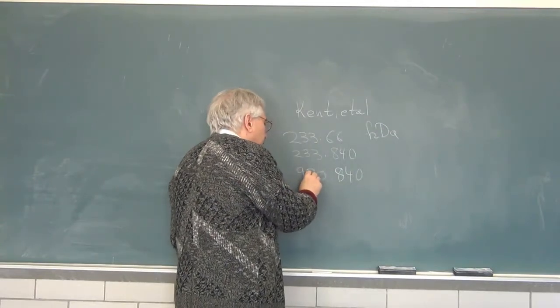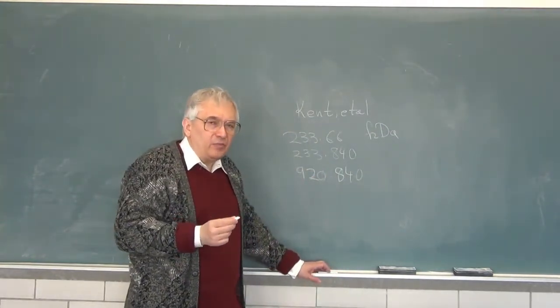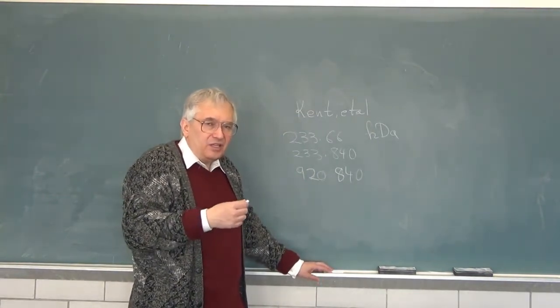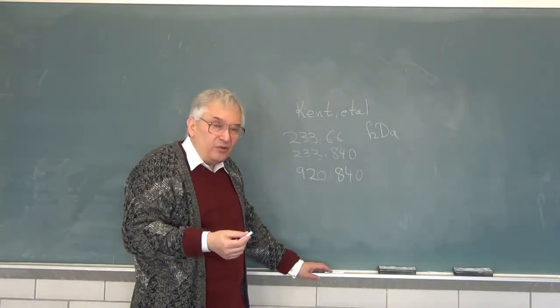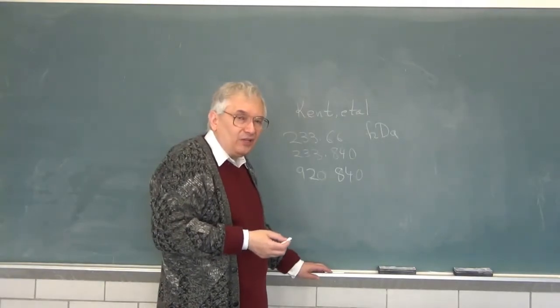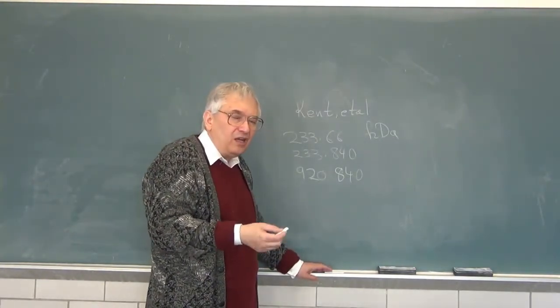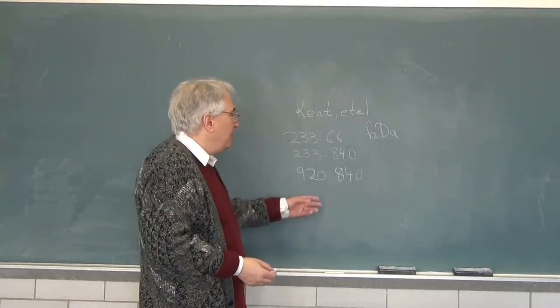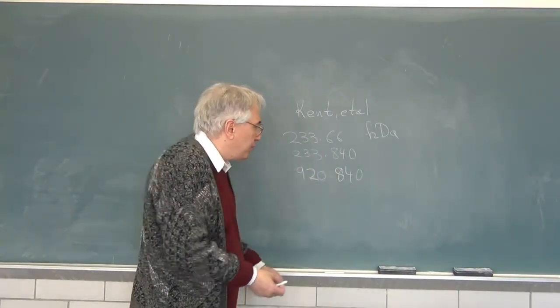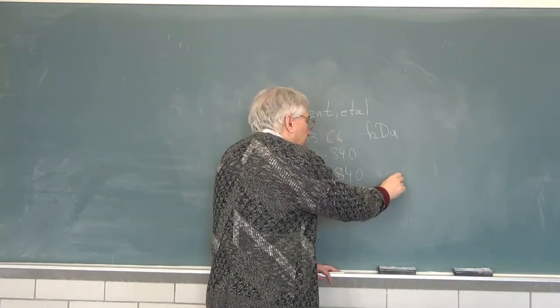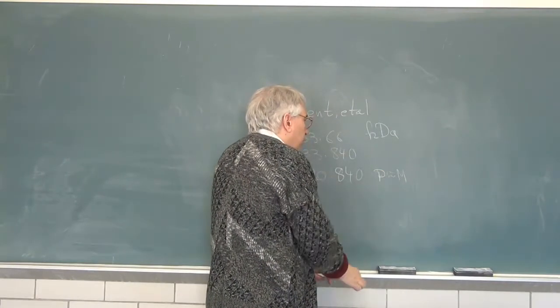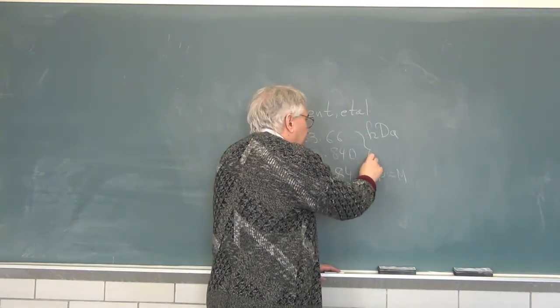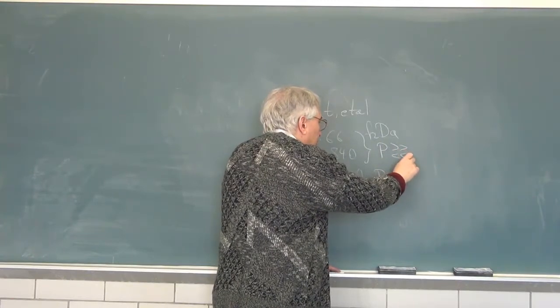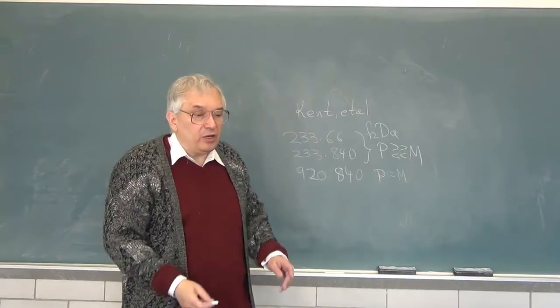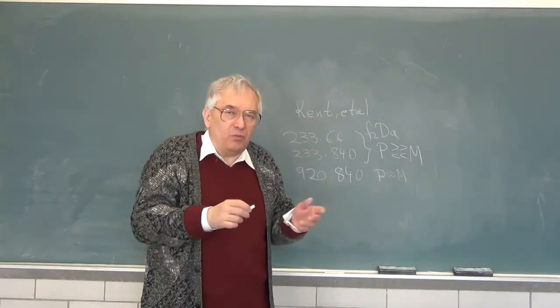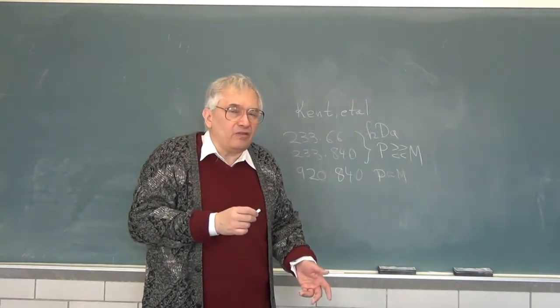Why are they like that? The first answer on why they are like that is you actually have to purchase or synthesize the polymer. Synthesis is a chore. Purchasing, you're limited in what you can buy. And you find polymers of particular molecular weights, and you take as much advantage as you can of what you have either bought or made. The second point is that these combinations actually do have a pattern to them. Here, the probe molecular weight and matrix molecular weight are about equal. Here and here, we have the probe molecular weight much larger or much smaller than the matrix molecular weight. That is, we are looking at three cases in which either the probe and matrix are about the same, or the probe and matrix are very different from each other.